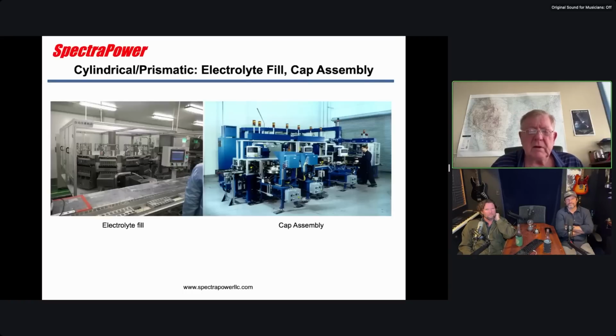And then this is cylindrical electrolyte fill. You can see it's a big rotary dial. Filling is kind of a problem for lithium-ion because they're so densely wound. So what happens is you pull a vacuum on the cell, and you inject electrolyte, and then you let it sit. You only inject about a third or half. It goes around this dial, which just takes time, and then you fill it again. And so you may have to do that 3 or 4 times.